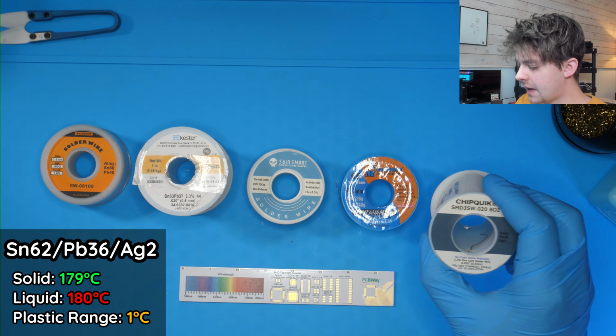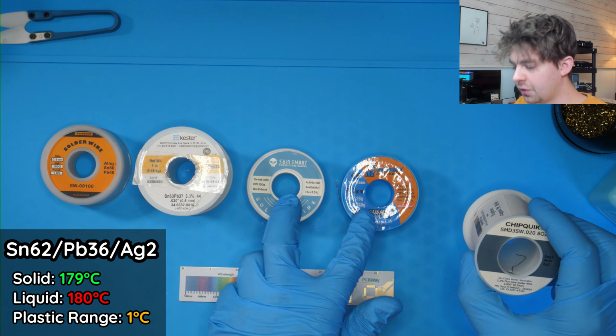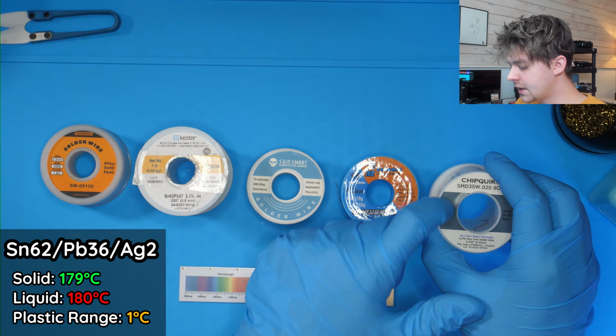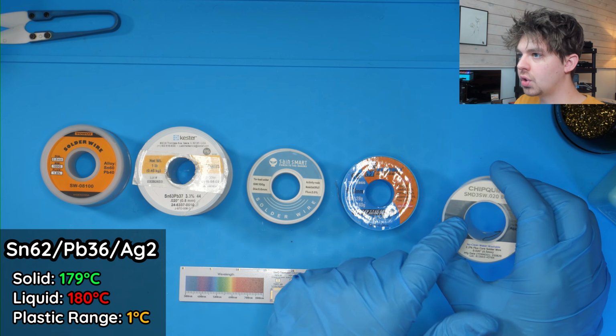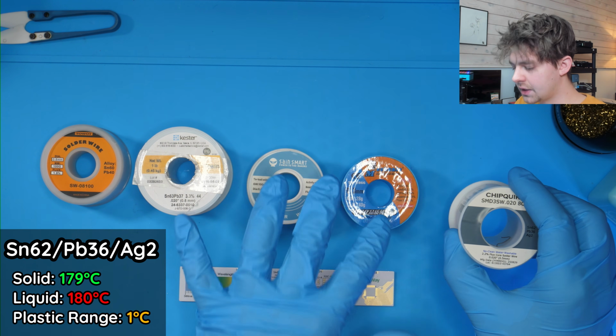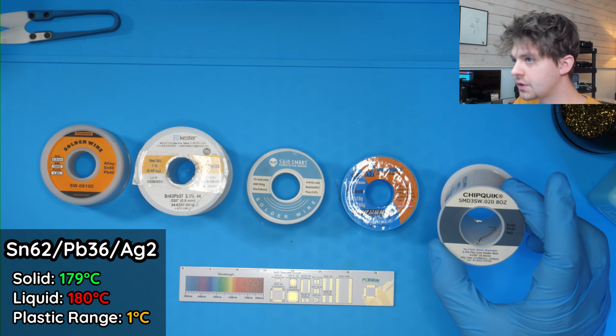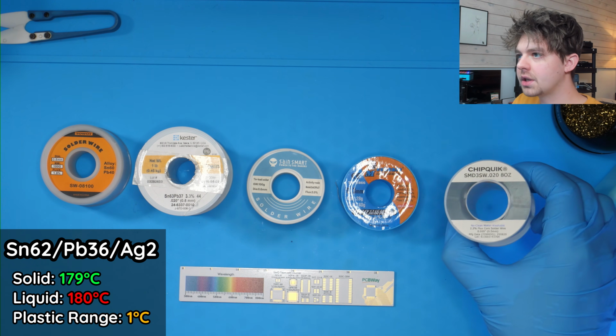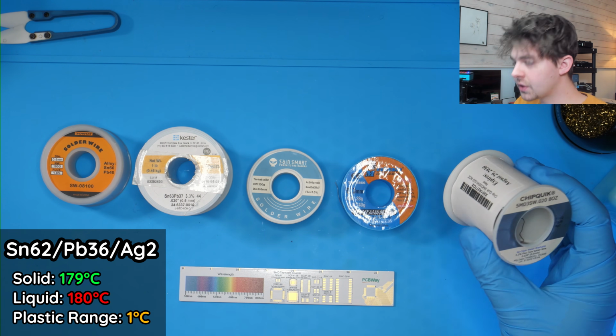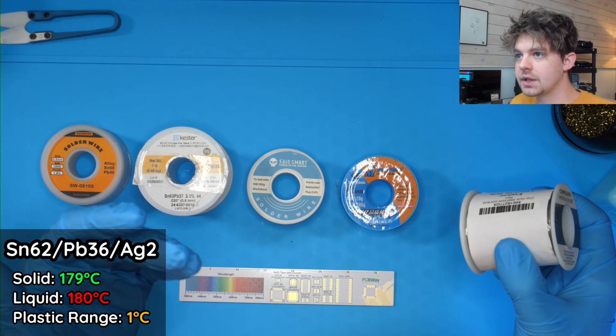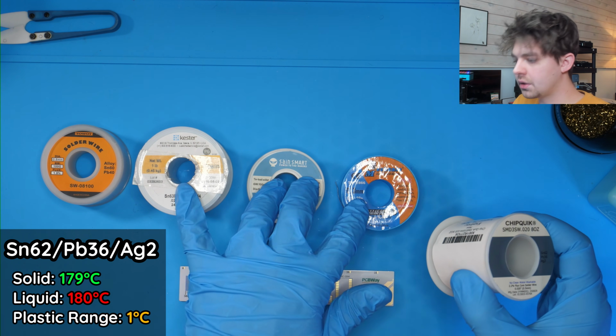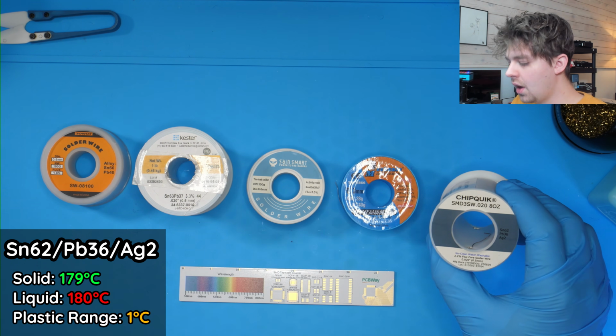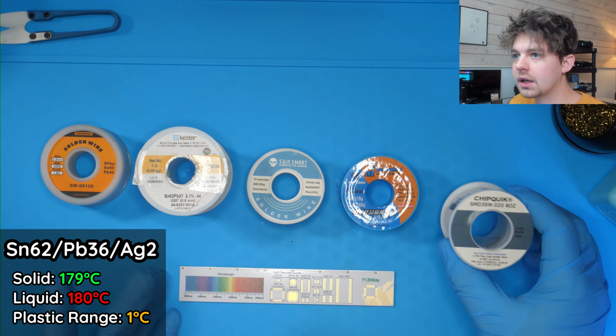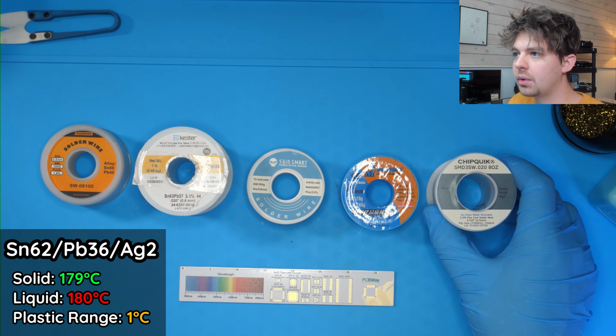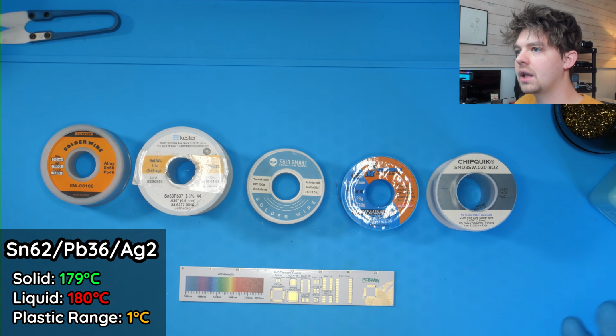Some of the main benefits of having the silver in here versus just having the fully Eutectic alloy is that this is actually going to make some more strong joints, some more reliable joints than the 6337. So it's a bit more resistant to microfractures and things. Not to mention, for the sake of repair work, it actually melts at a slightly lower temperature, 3 degrees Celsius difference between the 6337 and this stuff with the silver in it, which I know 3 degrees Celsius doesn't sound like a lot, but it can be quite a lot when you're dealing with retro boards and things that are prone to delamination and, you know, really sensitive components and things like that.